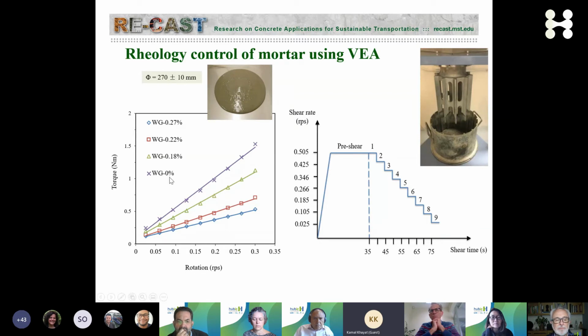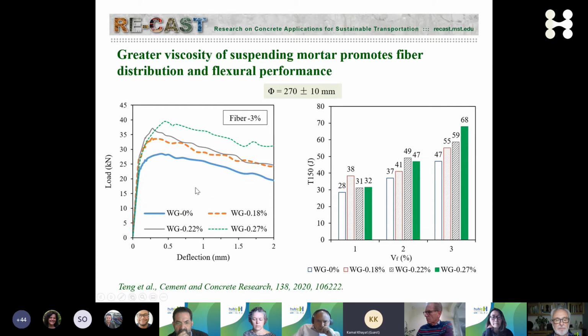So by using some viscosity enhancing agents, we can enhance the viscosity of the concrete. And by doing that, we can increase the flexural strengths and the toughness. For example, here, if you don't use any viscosity modifier, you have a flexural strength of about 27, 28 kilonewton. So this would be about 30 megapascal in flexural strength. By adjusting the viscosity, adding welan gum, you can see that you can quite a bit increase the flexural performance because you're aligning the fibers in the direction of the tensile load, and you're also increasing the toughness a lot. Okay, and this is for 1% fiber, 2% fiber, 3% fiber, depending on the structure applications. We use 1% all the way to about 3.3% steel fibers, and these are the microfibers that are 13 mm in length.